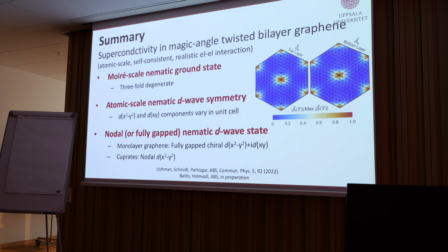And it's, as you see, very different from monolayer graphene, where I would have a fully gapped chiral state, and then the cuprates, if I did the whole thing on the square lattice, I would get a nodal D-wave state, and there would be no competition. So by just changing the atomic structure of the system or making this big Moiré cell, I actually get a very different superconducting state with the same assumptions. So with that, I thank you for your attention.